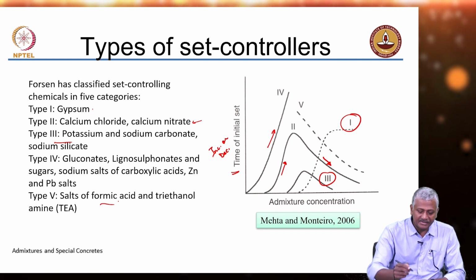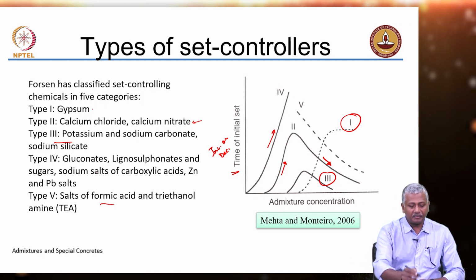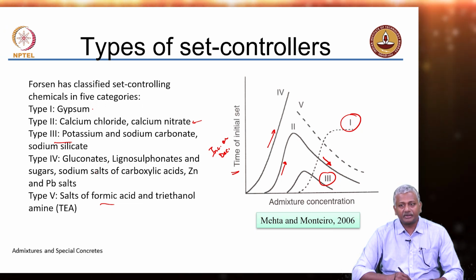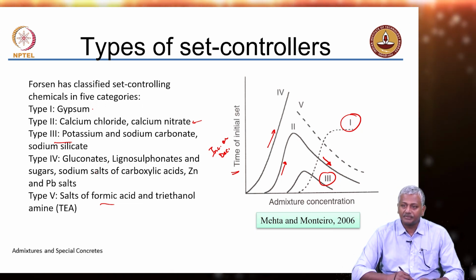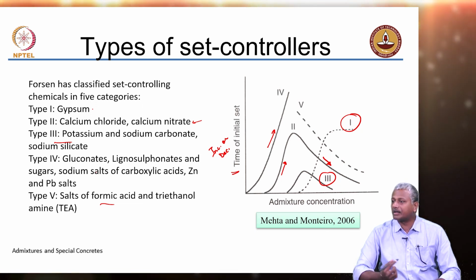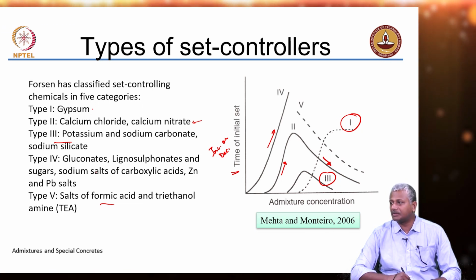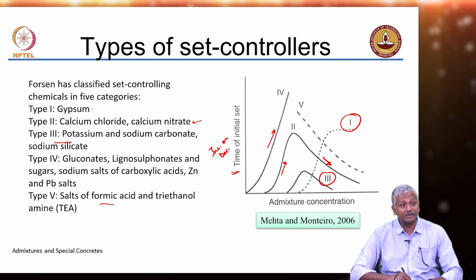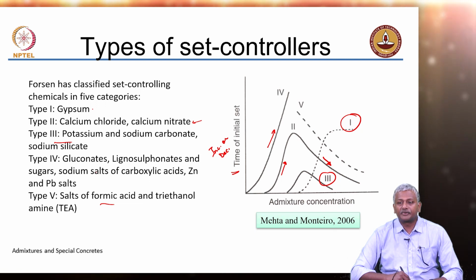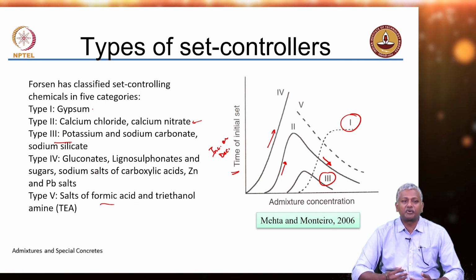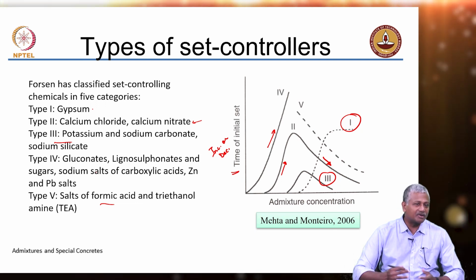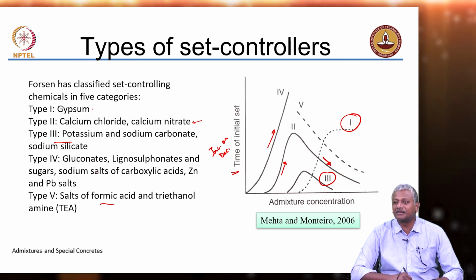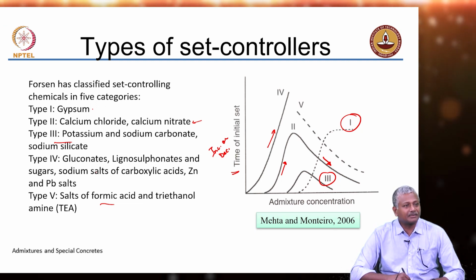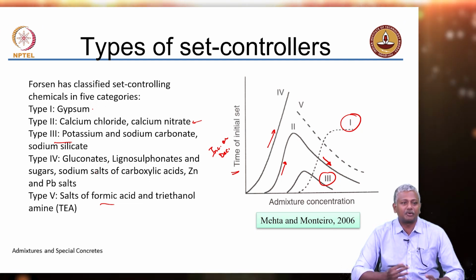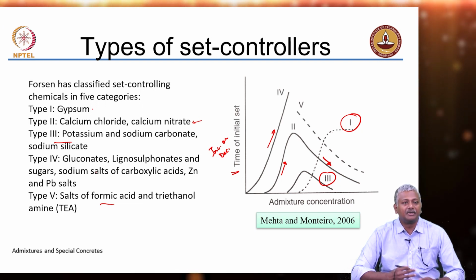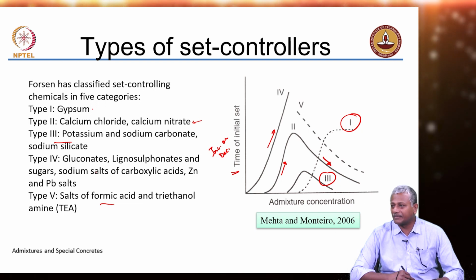These are salts of formic acid and triethanolamine, whereas type 4 are basically your major retarders that are typically used. Lignosulfonates, sugar is a very well known retarder. Most truck drivers carry a packet of sugar with them to prevent the concrete from setting inside the plant, inside the truck, right? Because wasting concrete is obviously much more preferable than wasting the truck. If concrete solidifies in the truck, that is a loss of several lakhs of rupees, whereas regular concrete, which is about 5,000 rupees per cubic meter, it is only about 30,000 rupees that you are losing if the concrete gets wasted.